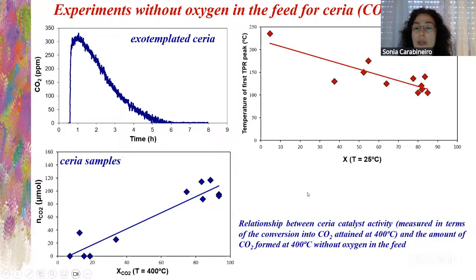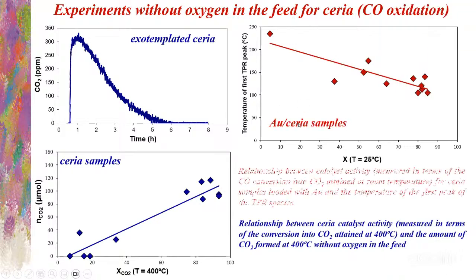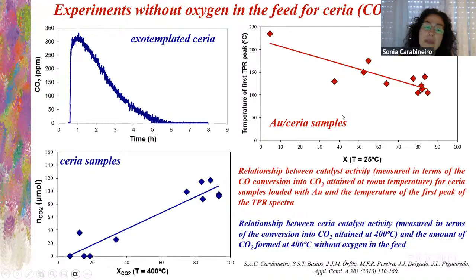If we do that for the gold-containing samples, we find also a relationship, not really a correlation. This is not an R squared of 0.999. No, it's just a tendency. We see more or less a tendency between the temperature of the first peak of the TPR and the activity measured at room temperature.